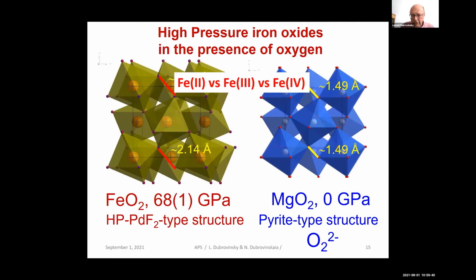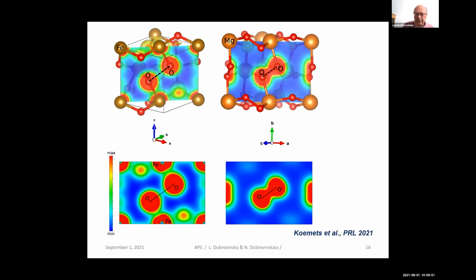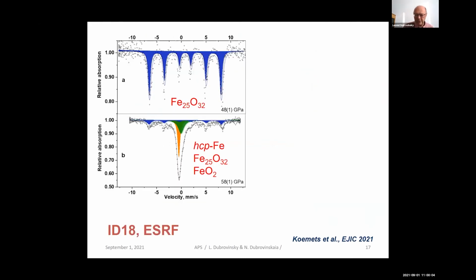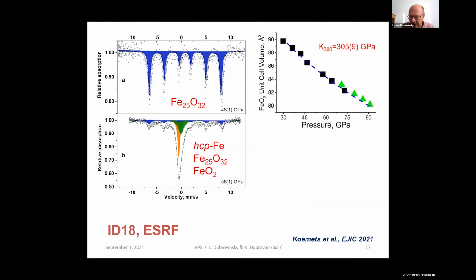We still don't know if we are dealing with iron 2+, iron 3+, iron 4+. And what is the oxidation state of oxygen. Theory suggests that not only MgO2 and FeO2 are significantly different, it's telling us that there are no real bonding between the oxygen atoms. Mossbauer spectroscopy shows us that there is this green component which we attribute to FeO2, and it means that iron is in the 3+ oxidation state. The same is told by the measurements of compressibility of this material. It's on the order of 300 GPa, and it means that this is certainly not an Fe2+ compound.